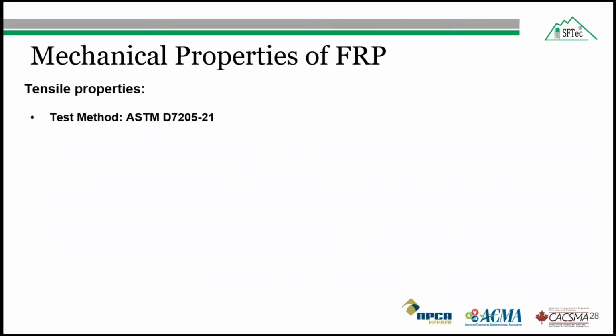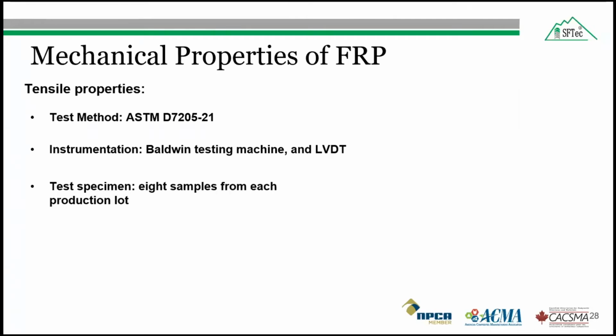The first test is the tensile properties of the fiber reinforced polymer specimens, and these are tested with ASTM D7205. Generally the instruments required are the Baldwin testing machine, or we can say the tensile testing machine, and an LVDT. The LVDT is required for recording the elongation or displacement. Similar to the physical properties, here we also need 8 samples for each production lot.